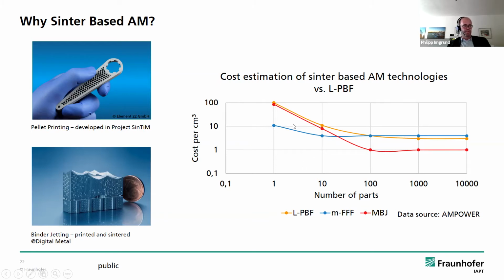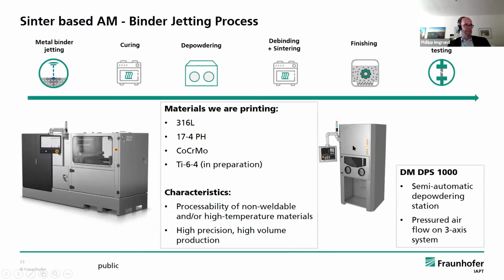And the binder jetting process is really getting you to lower cost, about €1 per cubic centimeter in ranges of more than 1,000 parts if you want to produce higher lots, which is due to the fact that in this process you can put more parts in one powder bed, and you don't need so much post-processing to get rid of support structures than in the laser powder bed part. And so we're dealing with this process. We have the first materials at hand: stainless steels, cobalt chrome, and titanium alloys. We can also process non-weldable materials.